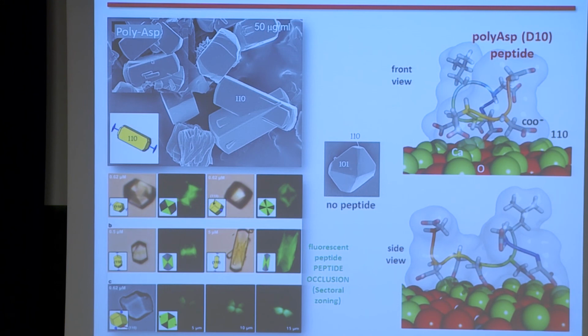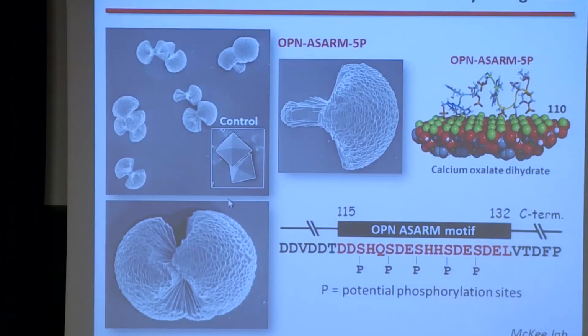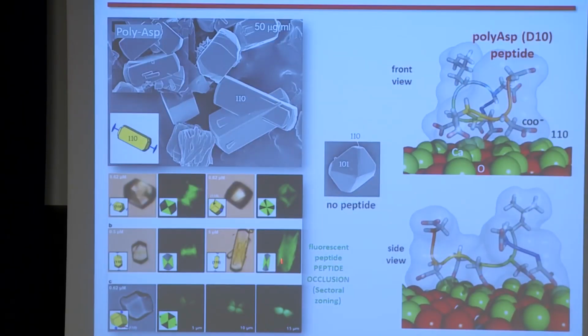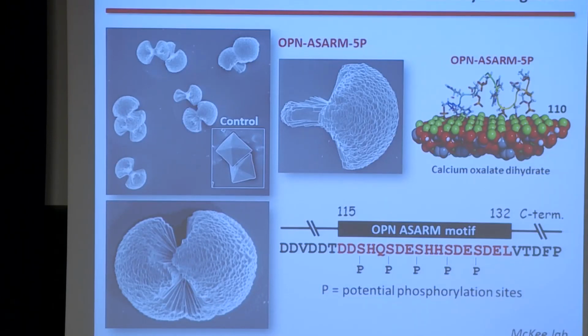Not only do they bind to the surface, but at low doses, you can actually see that they're incorporated by sectoral zoning into the individual crystals. You see there's more fluorescence. You can use a fluorescent marker on the peptide, and you can study how peptides are incorporated into a calcium oxalate crystal, peptide occlusion. It's very important and very interesting. And using Rosetta surface, we modeled how we think the polyasp binds to the calcium in the calcium oxalate 110 surface. Using our other peptide that we like from osteopontin, we grew crystals.